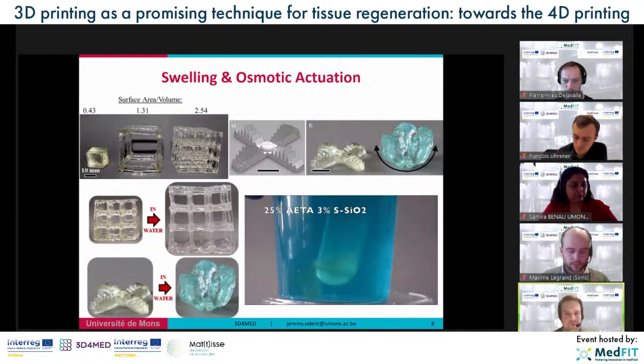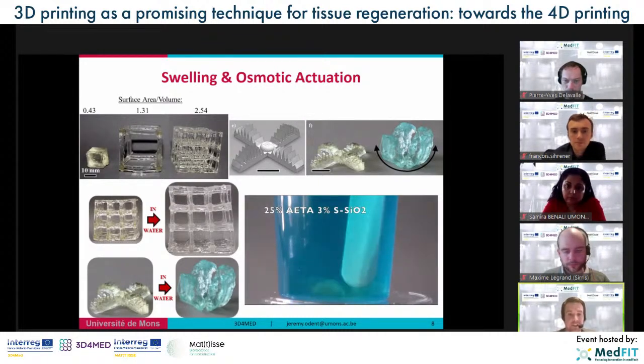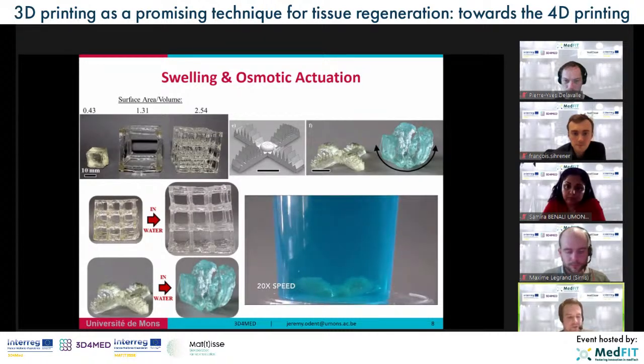We also use our ability to photo-pattern a 3D structure to print an osmotic actuator. Here, as you may probably know, we design some structures of higher surface area to volume ratio. And if we have a higher surface area to volume ratio, we will have faster swelling. So we control the diffusive swelling to design a multi-arm gripper, which is able to swell from a flat and open state to curved and closed within just a couple of minutes.